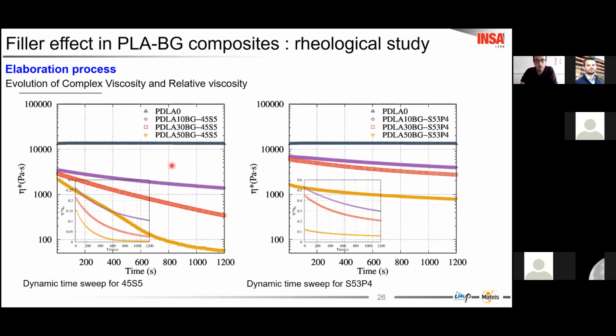Instead, for the bioglass composites, there's a decrease of viscosity from the beginning, and we can see that the degradation speed is faster in 45S5 than in the case of S53P4, showing faster degradation here than in the case of S53P4.